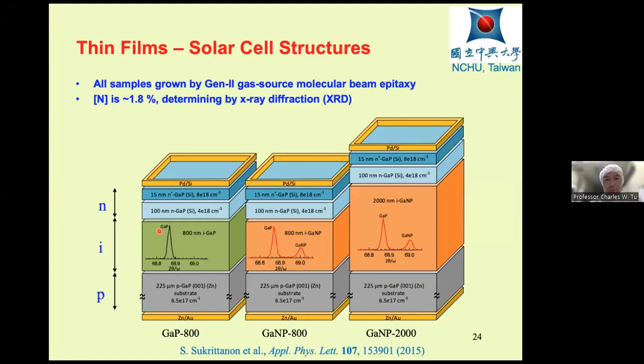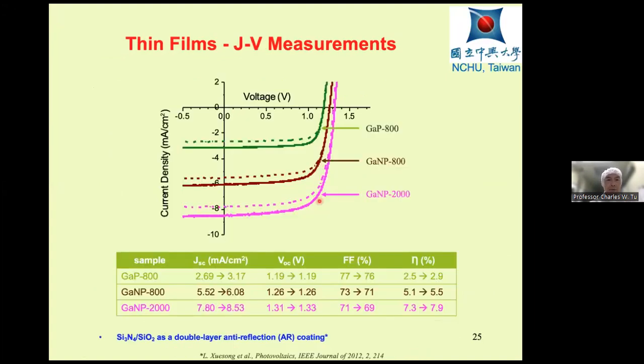One is just a gallium phosphide. The other one is a dilute nitride, and then we have a thicker dilute nitride. So we compare these three samples. Here is 800 nanometer, 800 nanometer, and 2000 nanometer. And here shows the